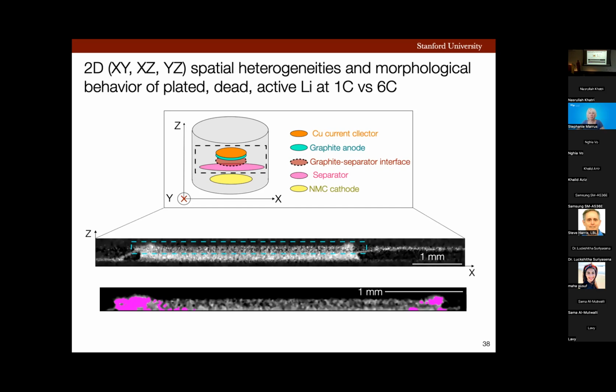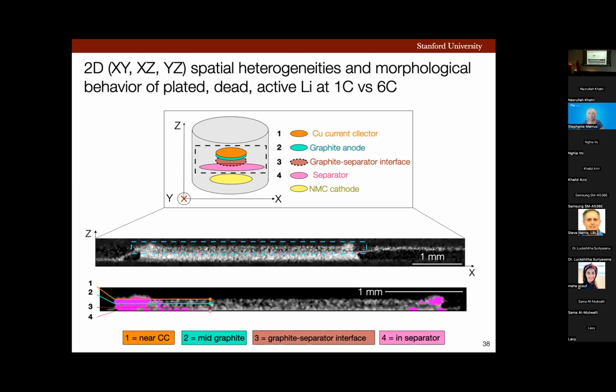Here I'm showing the cropped grayscale image of my battery with the colorized segmented pink regions. They are corresponding to plated lithium. Here, region number 1 is near the current collector. Region number 2 is mid graphite. Region 3 is the interface, and region 4 is the separator. Now, I investigated the 3D spatial heterogeneities at all these 4 different regions because it can tell me the direction in which lithium is plating in 3D. Now, let's look at the data in the XZ and YZ planes, which are cross-sectional views.